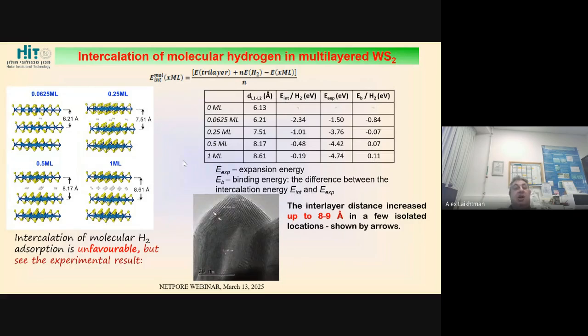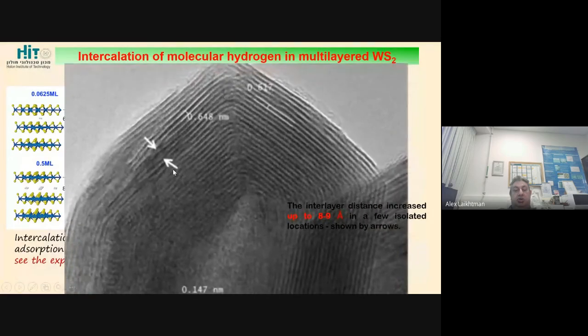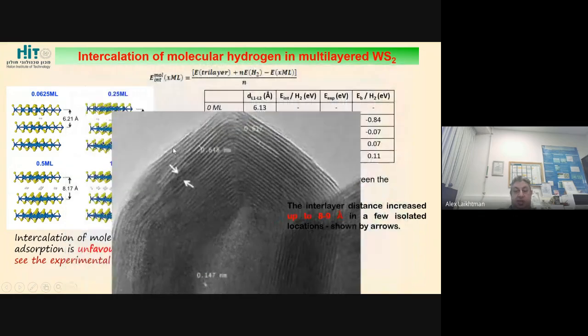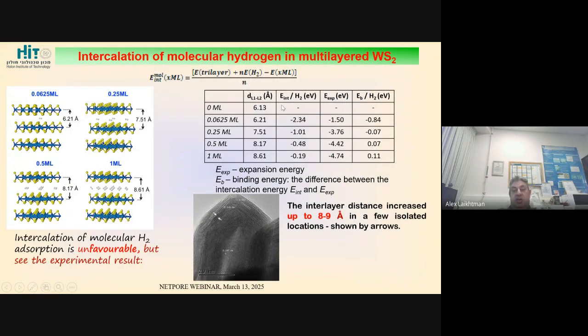single monolayer. On the other case, we were quite disappointed that this calculation showed that in the case of intercalation of hydrogen, so we consider that most of hydrogen will be intercalated, then in this case, the process is very non-favorable. We should get a negative energy, and this was quite disappointing. But then, using the experimental TEM, we obtained this expansion of the interlayer distance in some local sites, which is well predicted by the DFT. But DFT says that this extension is so energetically consuming that it will never happen.